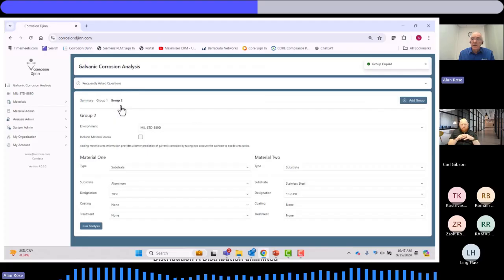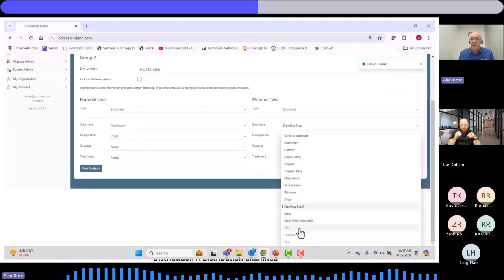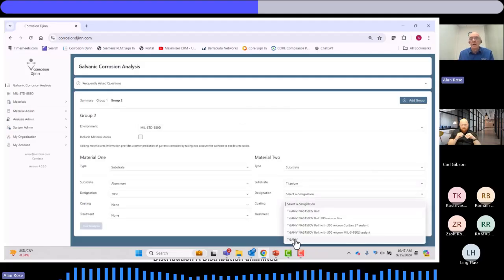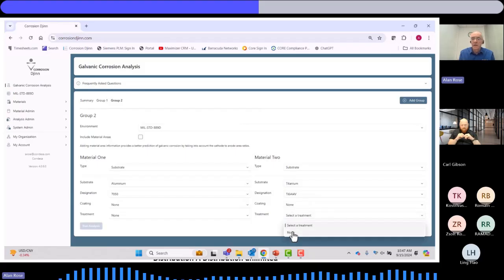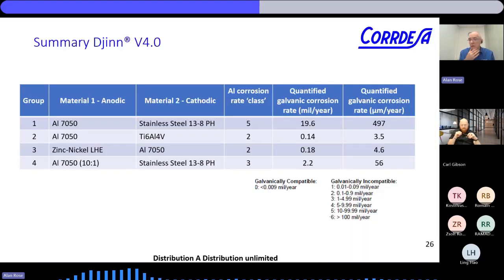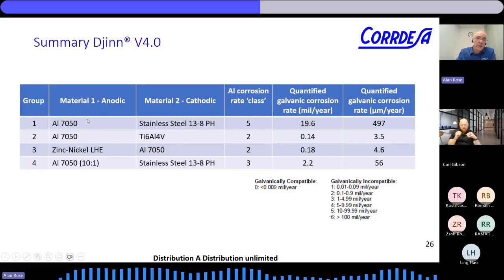And so you can quickly copy that group. It self-populates, and then you can say, oh, no, this time I'll try titanium, and then you can put in zinc nickel, and you can very quickly go through those options. So in a very short time, I've just got a summary of it here. I looked at aluminum. I'm thinking, stainless steel fasteners or some part of my structure. Aluminum with Ti-6-4, like we talked about earlier in the Navair example. And you can see very quickly what that corrosion rate is. So you get a quantitative number, and it also reports the mill spec number as well.